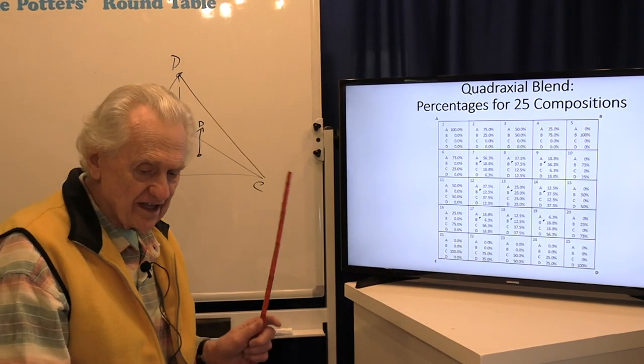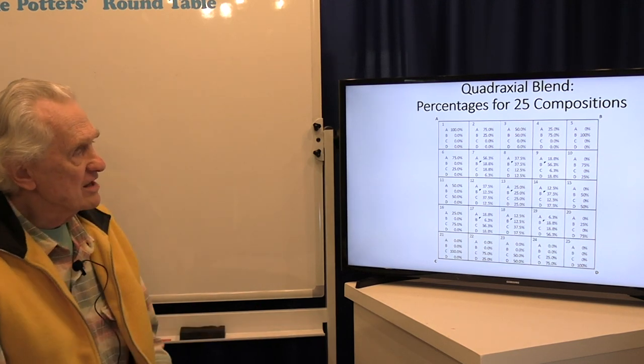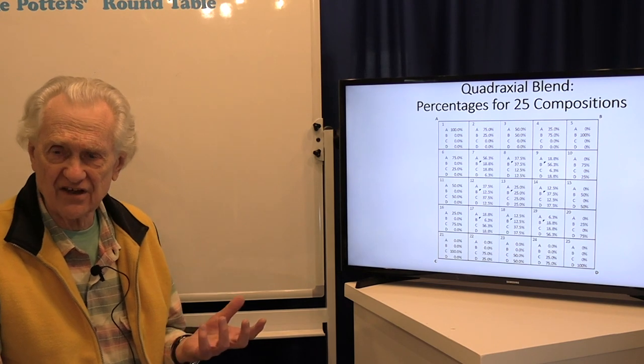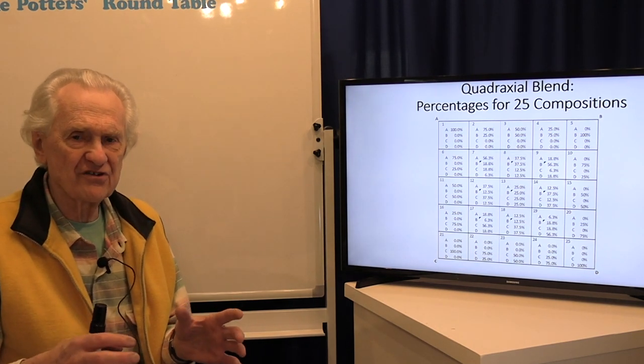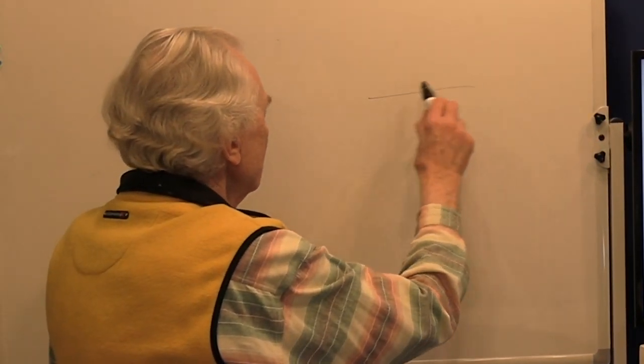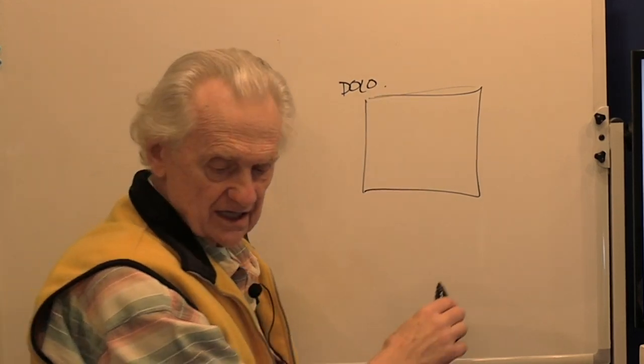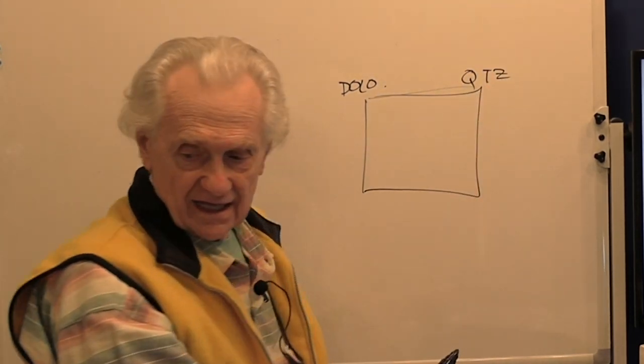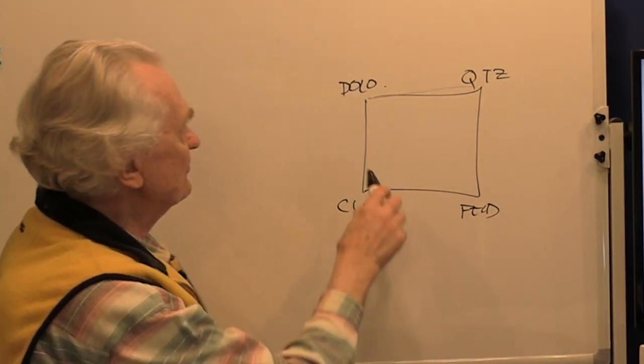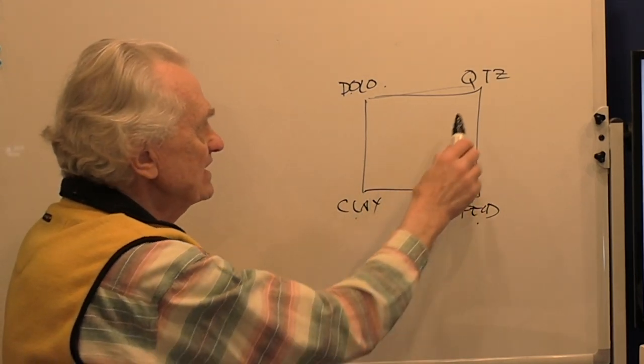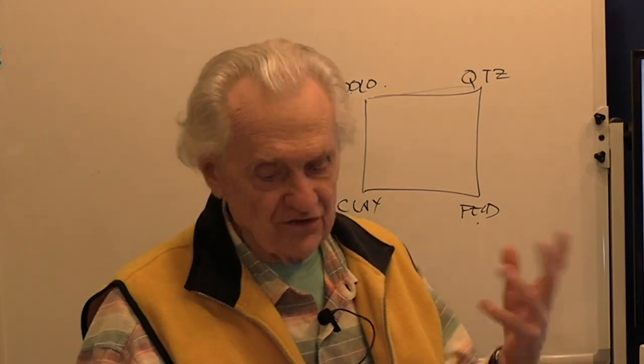As an example, when teaching a class we used quadraxial blends for glaze testing. I could set up a quadraxial blend with dolomite, quartz, ball clay, and G200 feldspar as a flux. In this case I have two fluxes — dolomite and feldspar — plus clay as the stabilizer and quartz as the glass former. This covers all three categories of materials needed in a Seger formula, giving me all the ingredients I need to potentially produce a glaze.